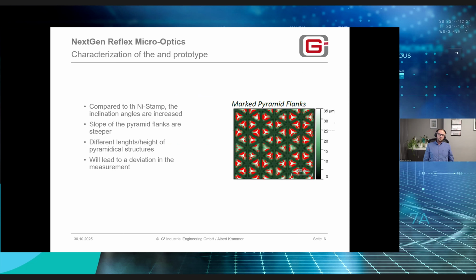The last step, of course, was the replication to get really some physical parts, and this was done by UV imprint technology. And what you can see here on the right side already is the microscope check of the physical parts of the prototypes. You see here the scale is around 30 micrometers, so you can see that the size of the pyramids is really around 30 microns.